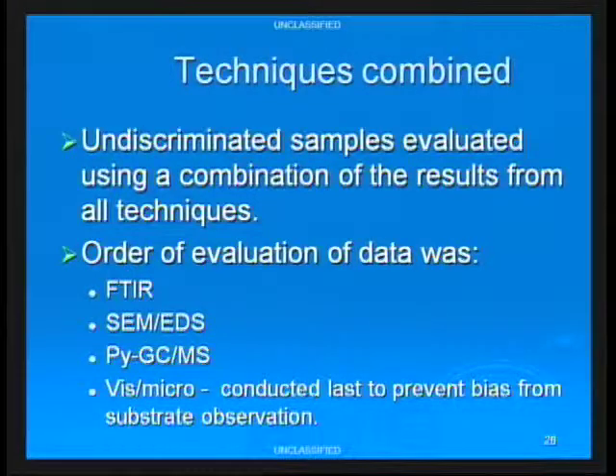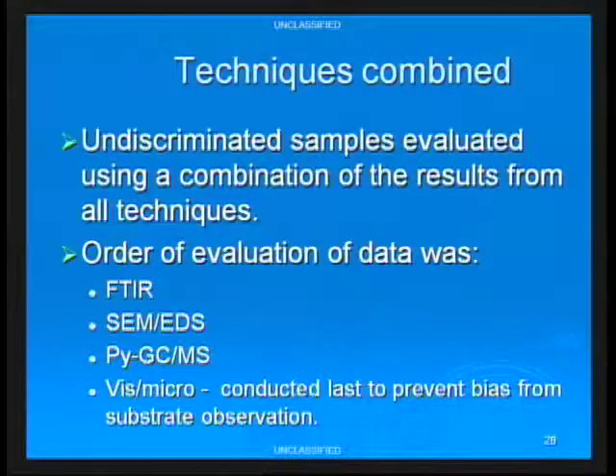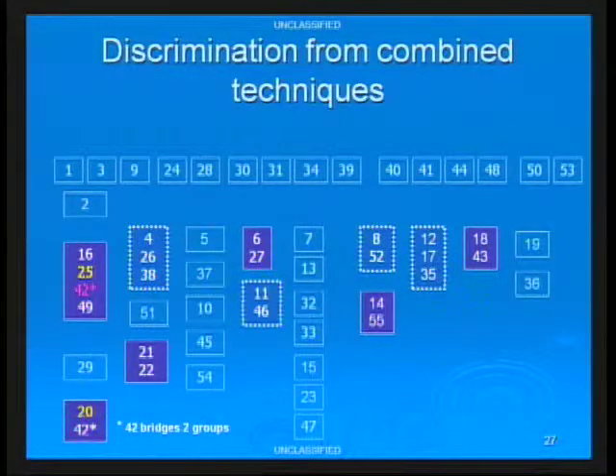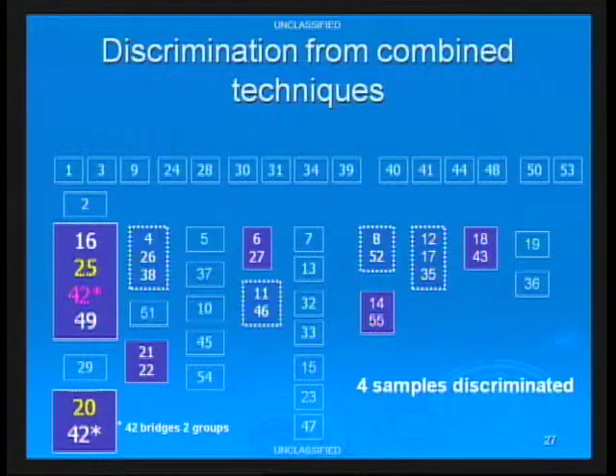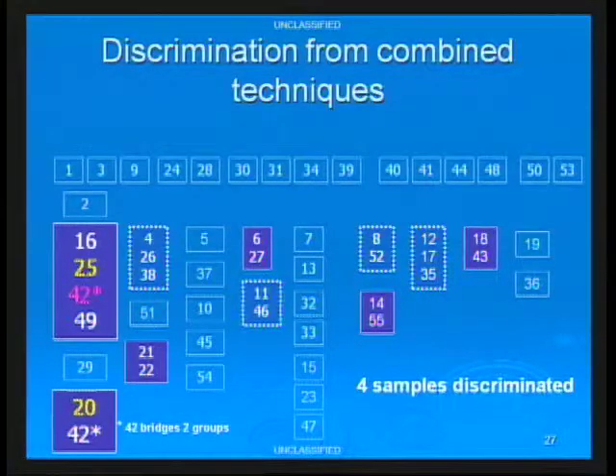So at the end, we went back and looked at the samples where we had been conservative — where we had subtle differences and kept them together — and asked, looking at the totality of exams performed, can we say anything more? Undiscriminated samples were evaluated using the combination of techniques. All instrumental techniques were assessed first, then visual and microscopical examinations, so nothing subjective was introduced first. Based on that, sample 42 finally gets discriminated — not just from one of the groups, but from both. In total, four additional samples were discriminated looking at the combination of techniques.